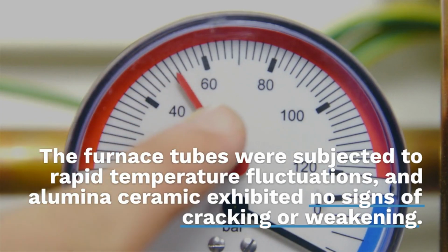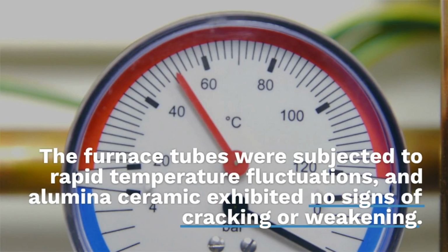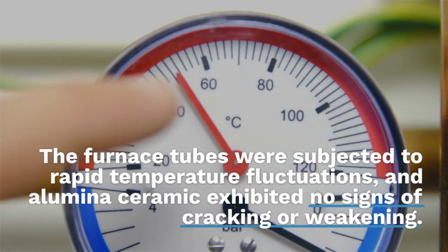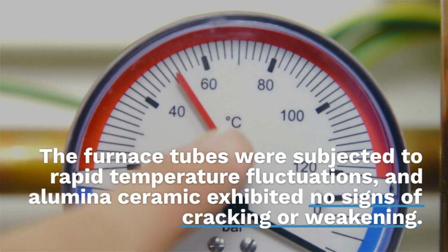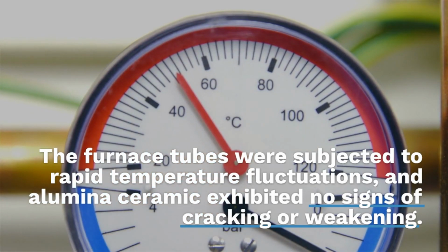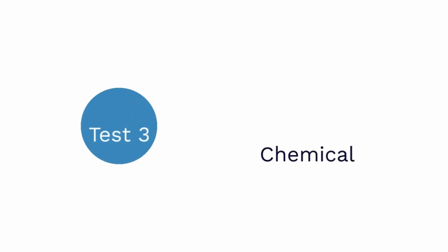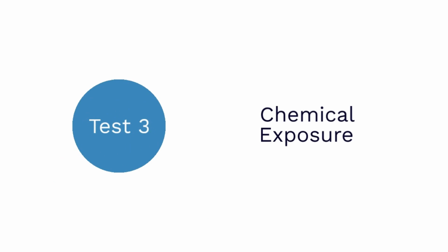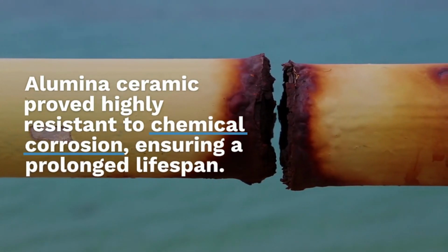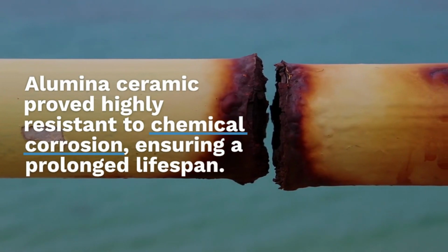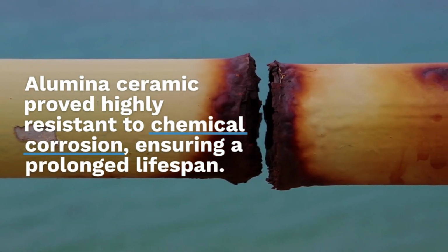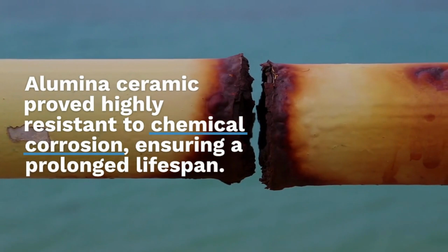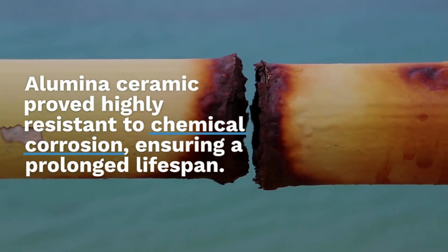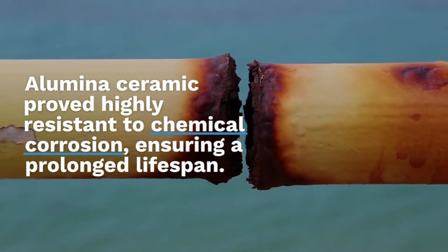In a more rigorous test, the furnace tubes were subjected to rapid temperature fluctuations. The results were impressive, as alumina ceramic exhibited no signs of cracking or weakening. To evaluate corrosion resistance, the furnace tubes were exposed to aggressive chemical environments. Alumina ceramic proved highly resistant to chemical corrosion, ensuring a prolonged lifespan.